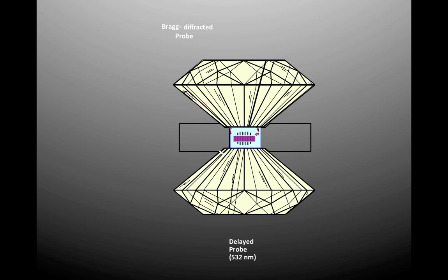These elastic waves modulate, like a standing wave, the local strain in the crystal, which perturbs the index of refraction, which gives us a grating off of which we can diffract. So a probe laser beam shining in transmits through the sample in a transmission body wave experiment, and some of the energy of the incoming probe is diffracted off of the grating caused by the acoustic waves in the sample.